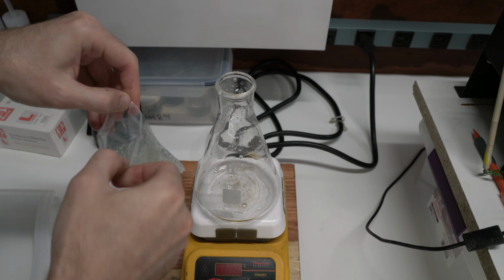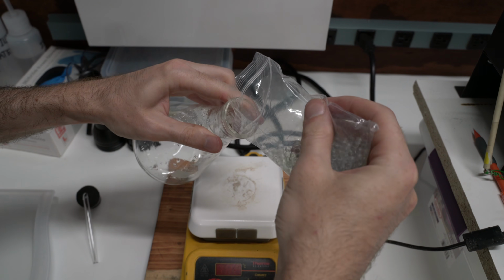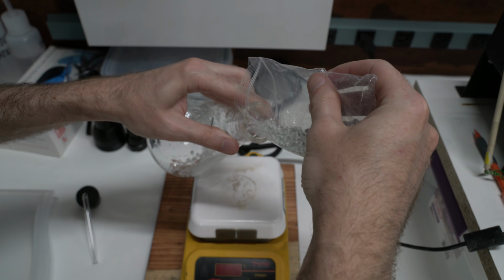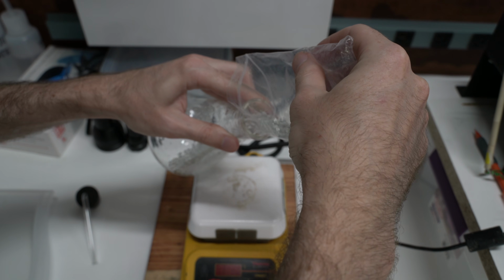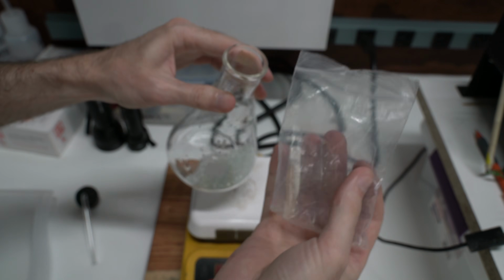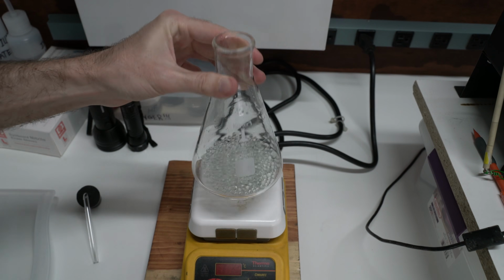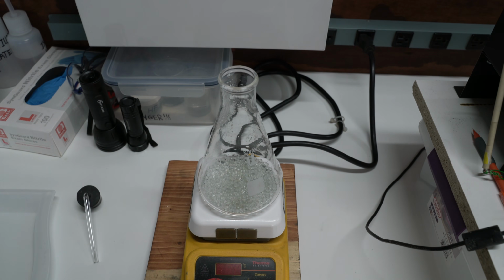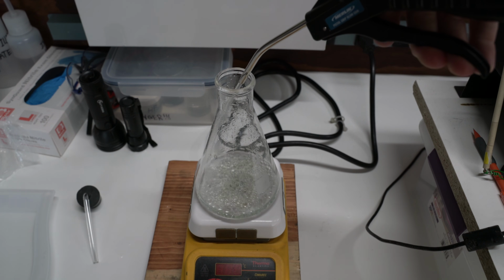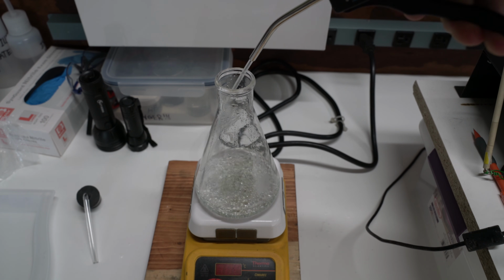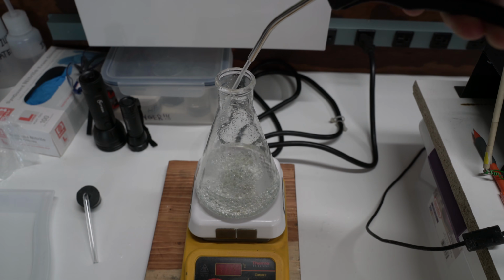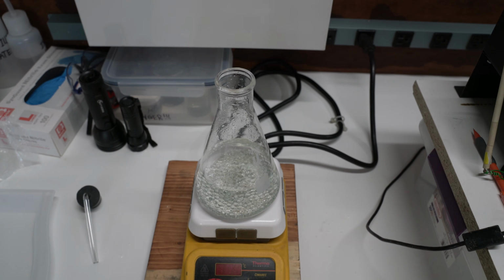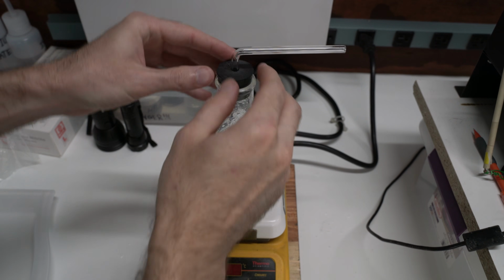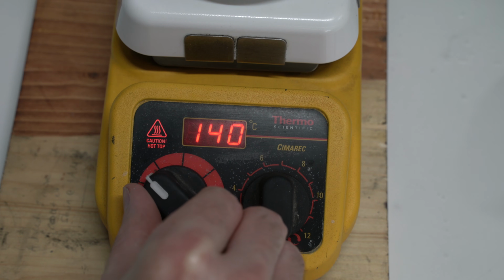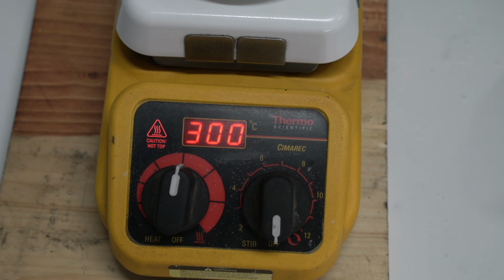Now, you can grow an oxide layer in air, but it'll go a heck of a lot faster if there's a little bit of steam in the tube as well. To accomplish that, I'm using an Erlenmeyer flask on a hot plate with some glass boiling beads and filling it with deionized water, about 200 milliliters or so. I'm using a rubber stopper and a right-angle glass tube to redirect the vapor into the tube furnace. Then I just crank the heat and wait for things to start boiling.